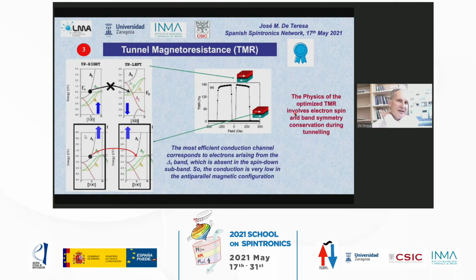So what is the physical explanation for this very high magnetoresistance? So here we have a low resistance in the parallel configuration and a high resistance in the anti-parallel configuration. So now we have to take into account that the conduction takes place through several subbands that exist at the Fermi energy in this material, in iron. So there are bands with different symmetries. They are called delta 1, delta 2, delta 5.